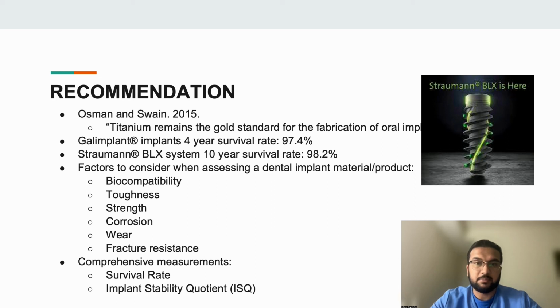While studies directly comparing titanium dental implant products from different companies could not be found, one study did find that Galimplant provided a survival rate of 97.4% after a 4-year follow-up, whereas the implant survival rate in immediate loading after 10 years for Straumann's BLX system was reported at 98.2%. While many factors such as biocompatibility, toughness, strength, corrosion, wear, and fracture resistance, just to name a few, ought to be assessed when selecting an implant material, the decision made by a dental professional will vary case by case.